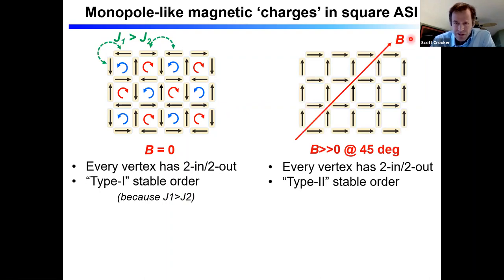Now, you can also easily convince yourself that if I was to apply a very large magnetic field along a diagonal, then this has to be the stable magnetic order. If you look, in this case, all of the elements are aligned either up or to the right because of this large magnetic field. Each vertex in this case also has two in and two out, but now the two ins are always side by side and the two outs are always side by side here. So this is also a stable ordering in a large field, but these are what we call type two vertices, all right?